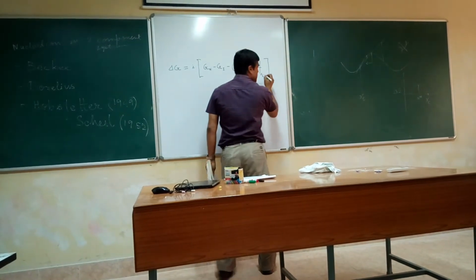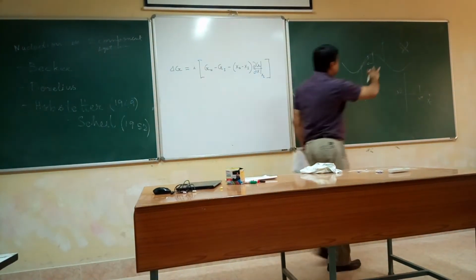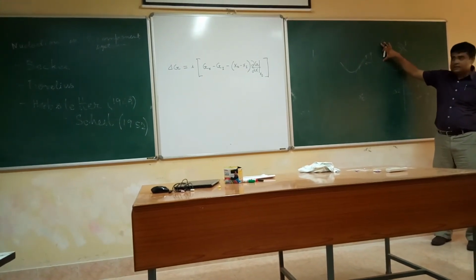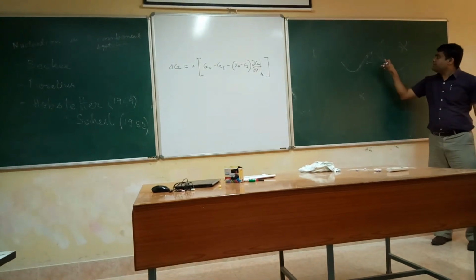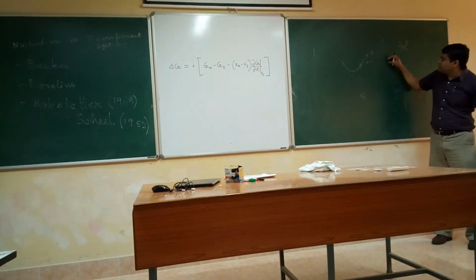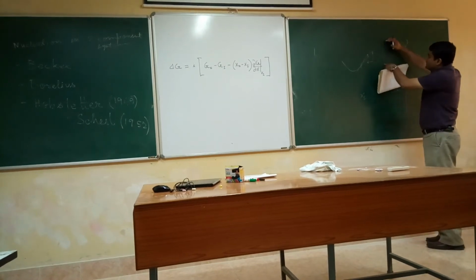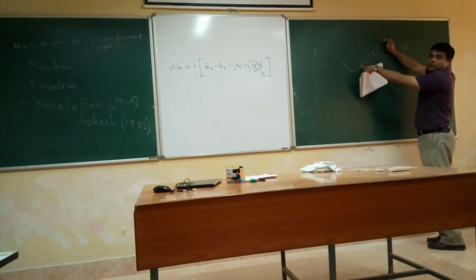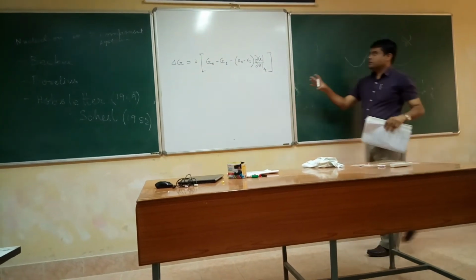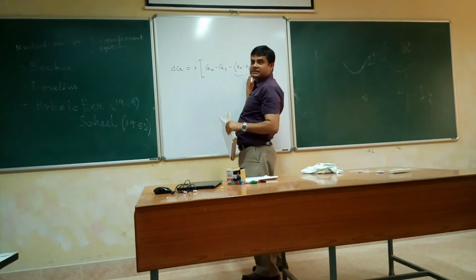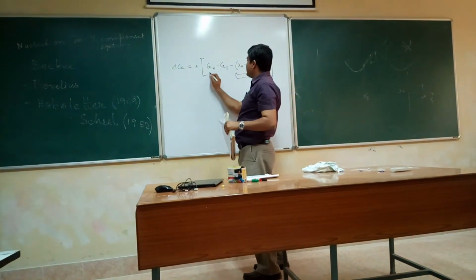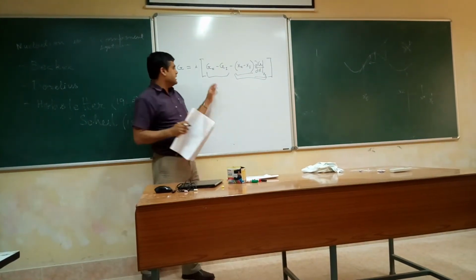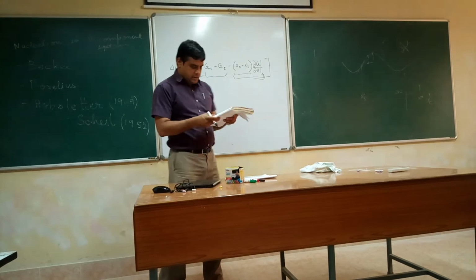That was the delta G beta. This length is nothing but Gn minus Gi, from here to here, minus this slope multiplied by this distance, Xn minus Xi. That length minus this length is that delta G beta.